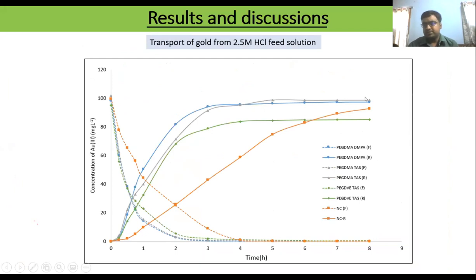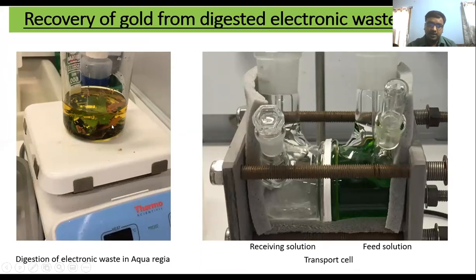That's how we initially screened these two cross-linked polymer inclusion membranes. And there are a lot more steps after that. I haven't shown the stages over here, because we need to do this before we move to the actual application part. What we had to do is prepare a solution which has identical acidity. Here we use a 2.5 molar HCl solution, but when we digest the electronic part, the acidity was around 6 molar HCl.